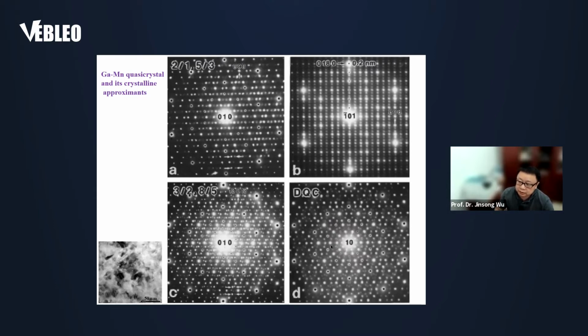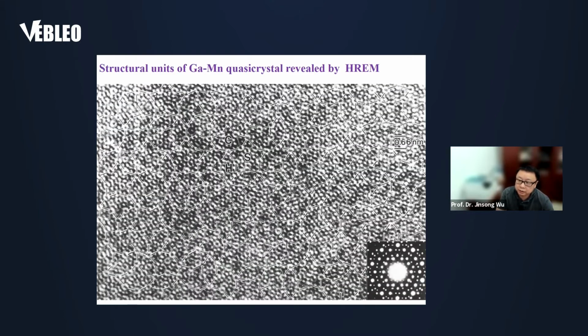So by using electron diffraction, we found the quasicrystal in a new alloy system, which is gallium manganese. And then we also applied high resolution electron microscopy to identify the atomic structure of the quasicrystal. And as you can see, the stacking of the structure units is not periodic, demonstrating that it has a quasicrystal structure.